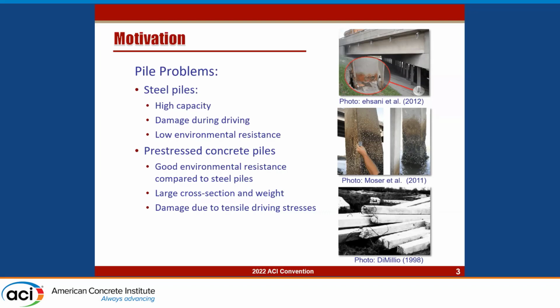Prestressed concrete piles are a different alternative to steel piles, and those have a relatively good environmental resistance compared to steel piles, although, as we can see in this photo, we do still have some issues with that. But prestressed concrete piles also have a larger cross-section and a lot more weight, and they also damage during the driving process from the tensile stresses that those piles experience. And there's a photo of some of those driving tensile damage on the bottom there.